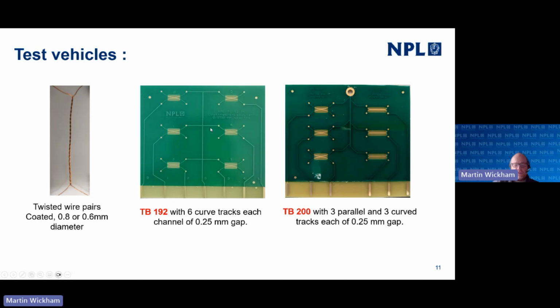The idea of the original design of these curved tracks was so that we were concentrating the field into where it's strongest, between the center of the curved tracks here. As you can see, that's not quite turned out as we expected it to, but this is where we started. We've latterly been looking at longer tracks, and what we tend to see here is that there's more opportunity for partial discharge to occur. So the inception voltage is quite often lower with these sorts of tracks than it is with these curved track systems.